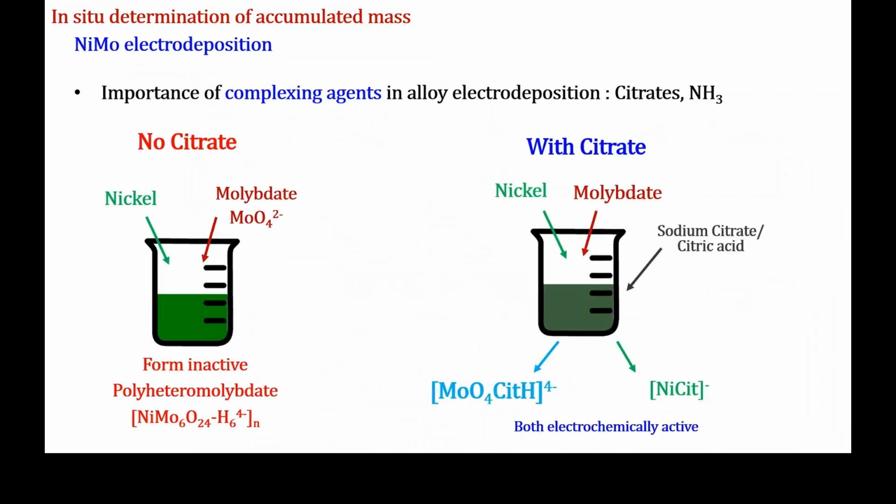And Namkang originally used a plating bath consisting of a nickel salt, a molybdenum salt, and boric acid in the acidic range, but found that he couldn't really get any kind of deposit that he actually wanted. So now he's gone into this lovely situation of adding complexing agents, including citrate and ammonia. So now we're in these potential pH diagrams, except we're trying to find out the data to make corresponding plots for molybdenum in addition to nickel.